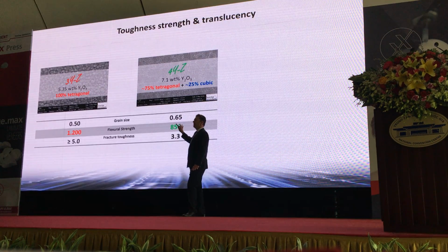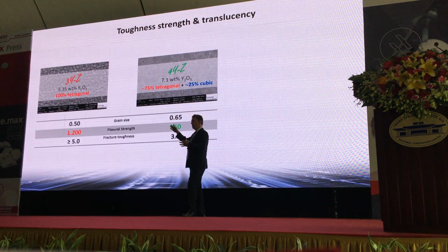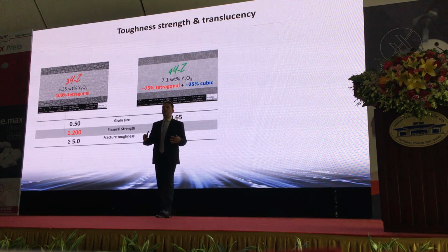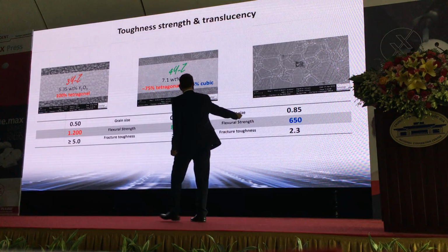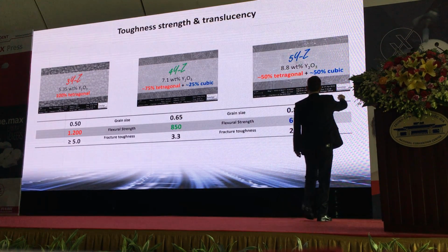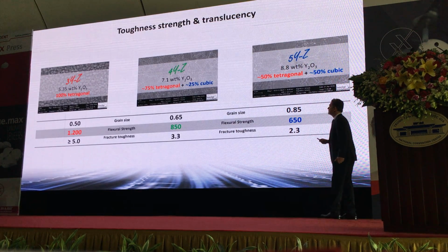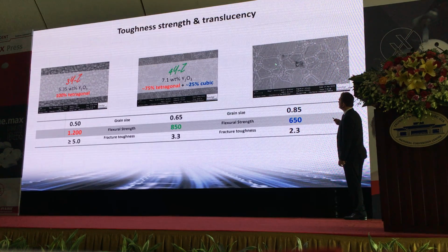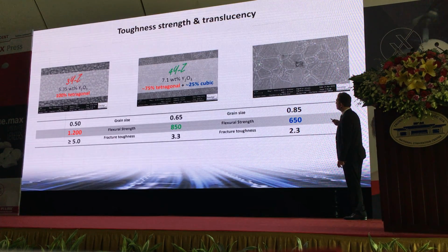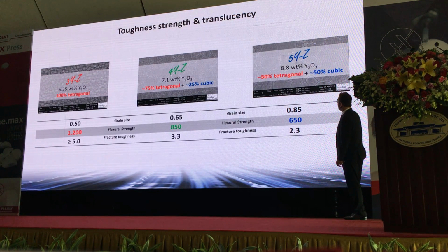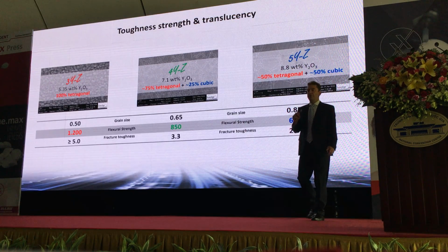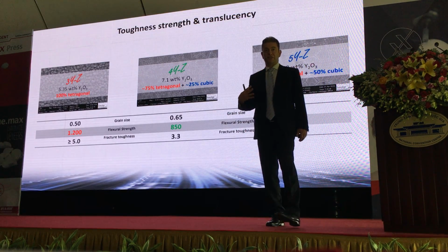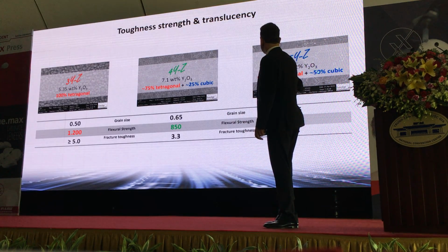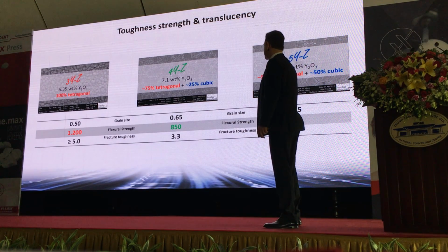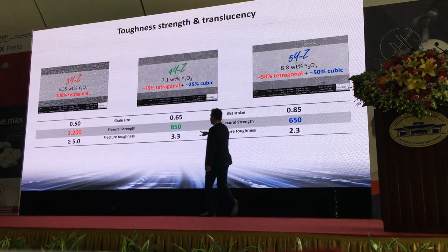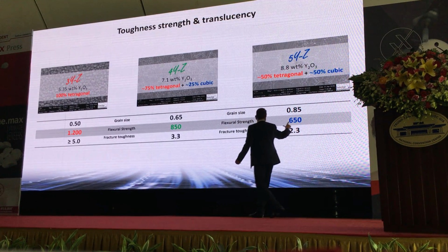If we want to make this material even more translucent, we can further increase the amount of yttrium oxide. Like here, you can see 5YZ, so it's 5 mole percent of yttrium oxide. And you can see the crystals becoming larger, even larger than here. Now we have a share of 50% of cubic crystal phase. So the material becomes even more translucent. But the strength, look at this. From 850, we can further go down to 650.